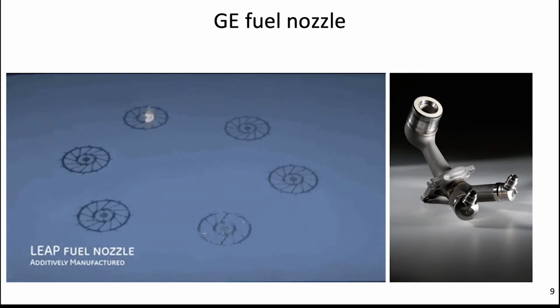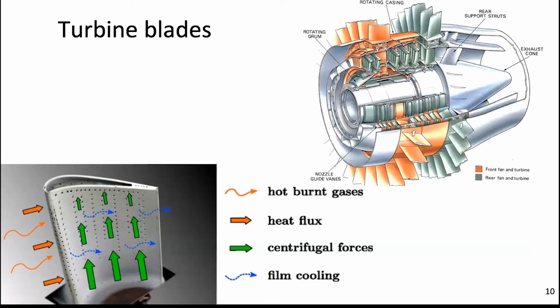And why is it real? Because in the fuel nozzle, in the inside of it, I can achieve this very complex morphology. And you can imagine that in a technology such as forging, I need to deform the material from outside and shape it. These sort of complicated shapes cannot be achieved with regular hot or cold working technologies, because there's no way to deform inside the material. Whereas when I'm building the material in layers, I can achieve these very, very complex shapes or topologies.